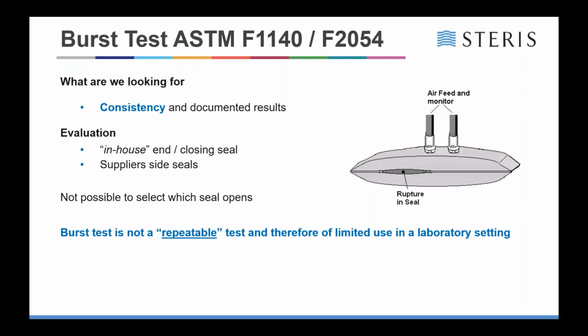Again, what you're looking for in either of the standards is consistent and documented results, whether it's your own in-house seal or a manufacturer's seal that's bursting. The one thing that you continuously need to do is monitor these results over time. Every batch that comes in, you need to be able to do a burst test on it and make sure that it's repeatable and within the limits you have set in your validations. Because if it's not, you're eventually going to get to a stage where you're no longer going to be able to use the actual pouches themselves.